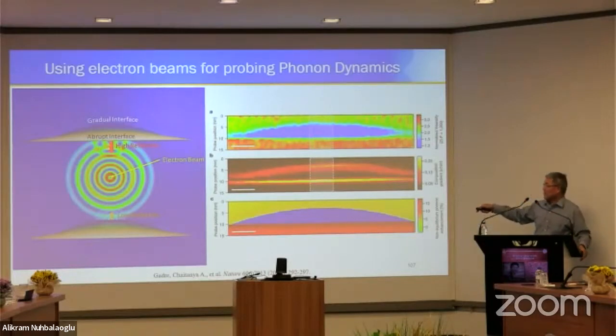So if a vibrational wave is generated in a crystal, and then you have two quantum dots beside it, this vibrational wave will reflect upward, and then see this direct sharp interface. And then this sharp interface is coherent, and there is a strong effect of reflection, like a specular reflection. This is a diffuse interface. It doesn't work like a mirror. Still have a bit of reflection, but not very strong.